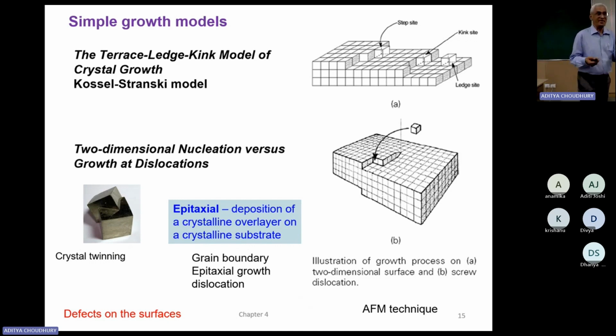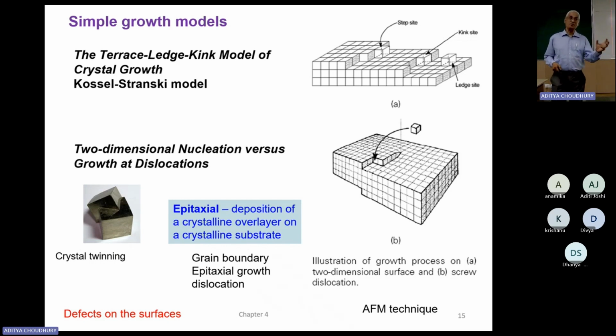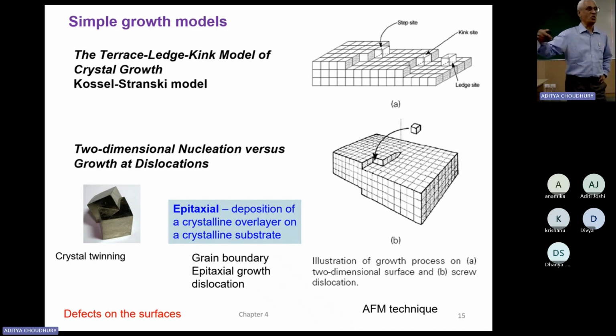But if you look at using SEM or something, or the same thing here, it looks really beautiful here. But you can start seeing the kind of mechanism, what kind of growth is happening. Once you have small crystal, you have all the experimental evidences. What we say is dislocation, actually, it is not dislocation. It's a mechanism of growth. We don't allow them to grow. We just take it out. That's it. And then even if you polish, you will have this kind of thing.